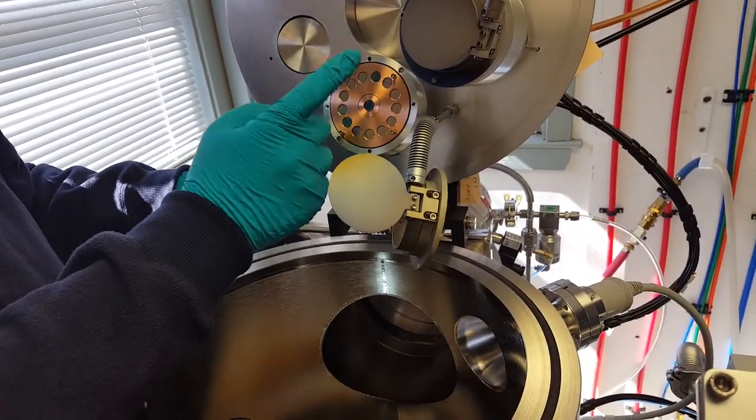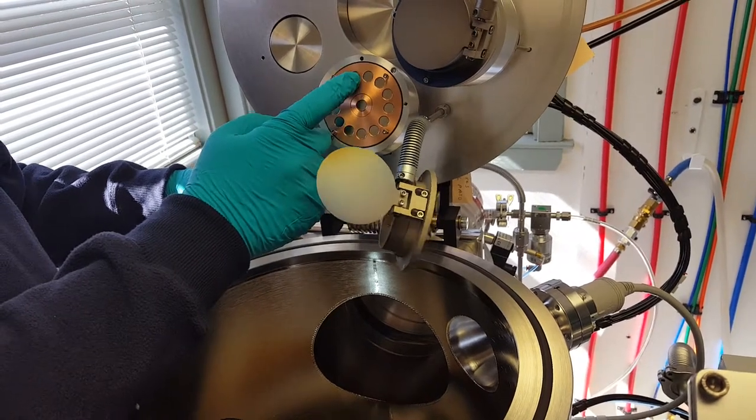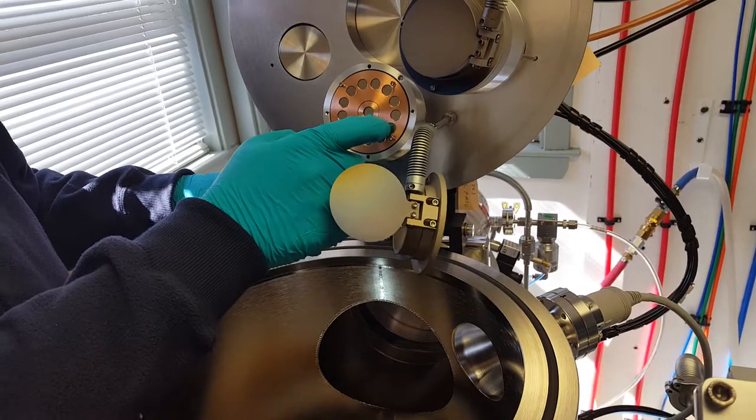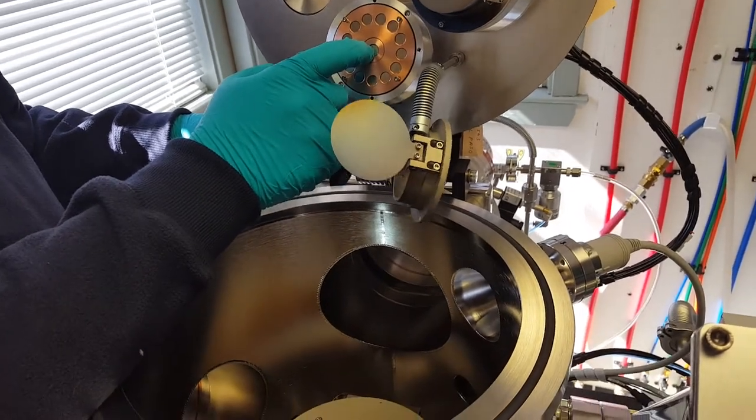These are, the spec is 3.7 to 4.2 kilogauss on each stack here and this one's like 5.3 kilogauss.